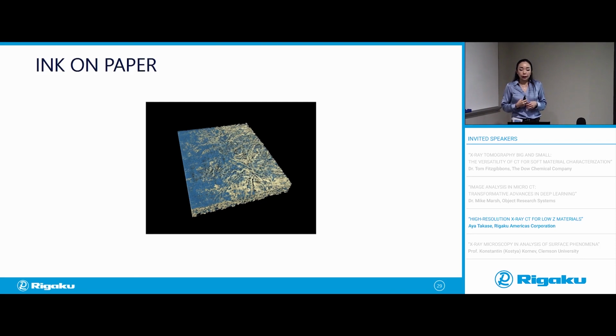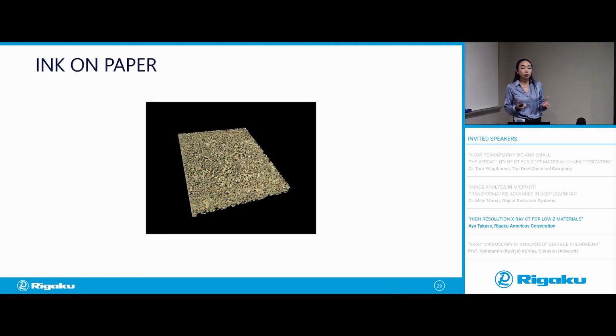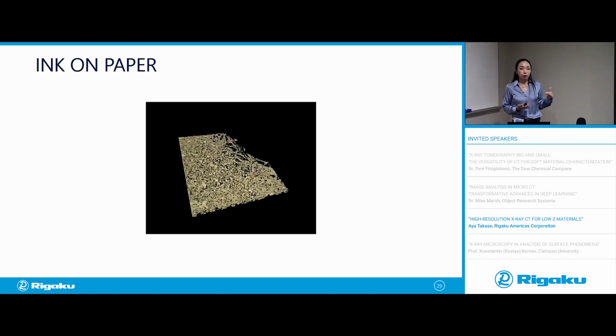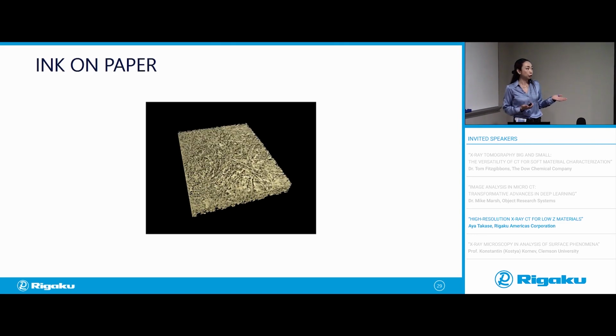This one is ink on paper. Paper is another low Z, low density sample. And with a low energy, high resolution scan, you can see the individual fibers in the paper, and also you can see where the ink is going in, how deep the ink goes into the fiber, and where it goes on.